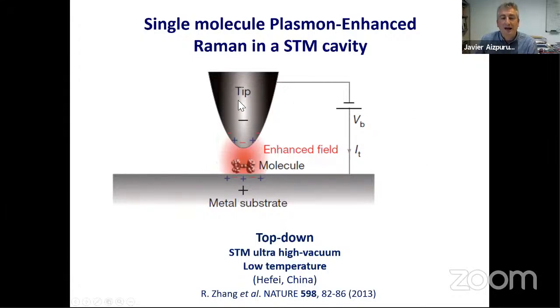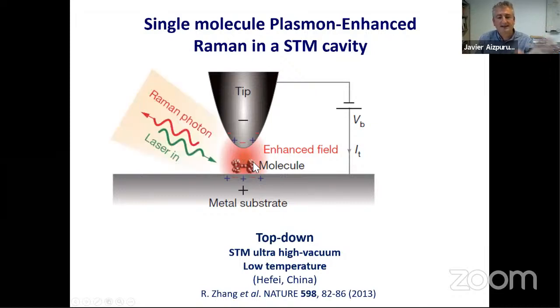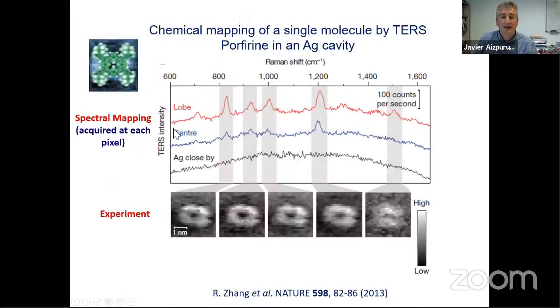This is, again, this extreme cavity, the plasmonic tip on a metal substrate. We put a molecule. And this experiment done 7 years ago by the group of Jianguo Hou in Hefei was a real breakthrough, right? Because they sent light in, they excited the vibrations of the molecule, Raman light was sent out with the phonons excited here, and they recorded this Raman photon map. And these are the Raman photon spectra, right, as a function of centimeters minus one, and they detected several vibrational fingerprints. When they scan the plasmonic tip, they manage to map every single vibrational mode within a resolution of less than 1 nanometer. This is optical Raman photon maps with a resolution of 1 nanometer.